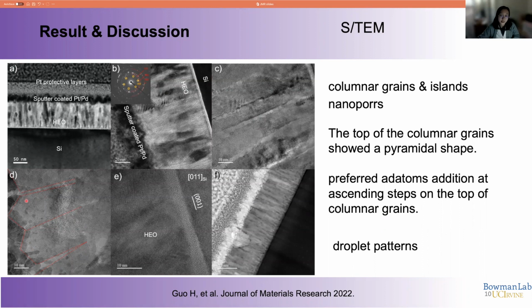There is an ES barrier at the edges of the columnar grains, which will impede the diffusion of adatoms to the edge sites, which will lead to these nanopores. Also these adatoms tend to grow on the top part of the columnar grains. That's why there is a very sharp tip at the middle part, but it is kind of low at the edge part because the energy barrier at the edge is different from that at the top, at the center part of the columnar grains.